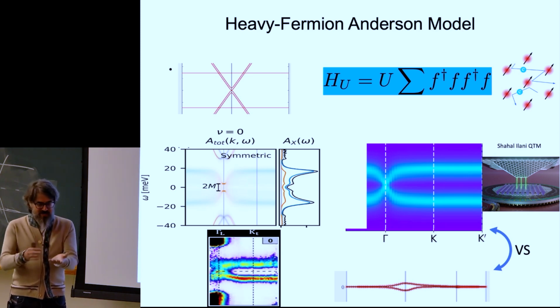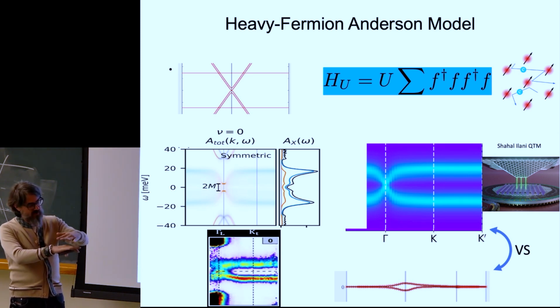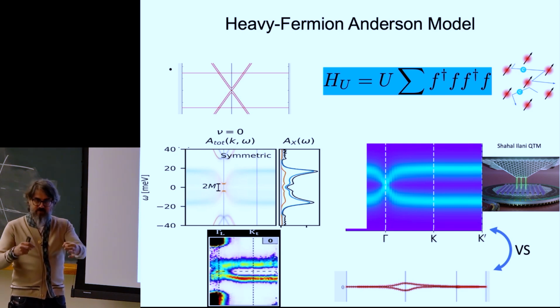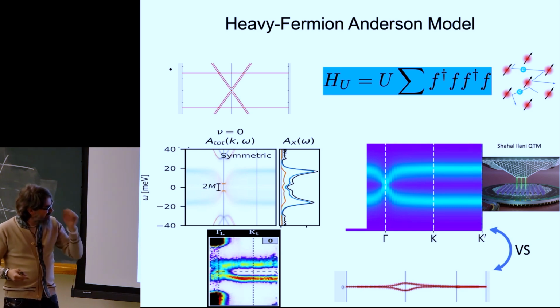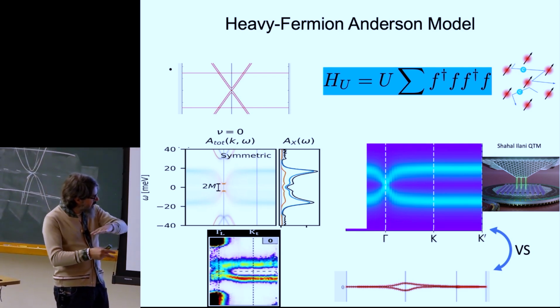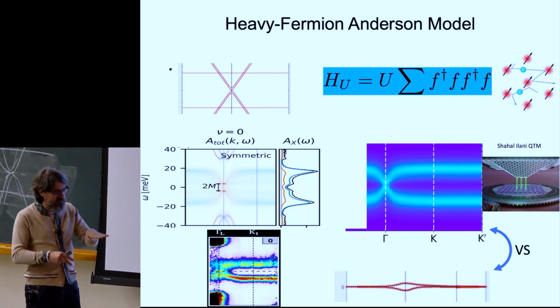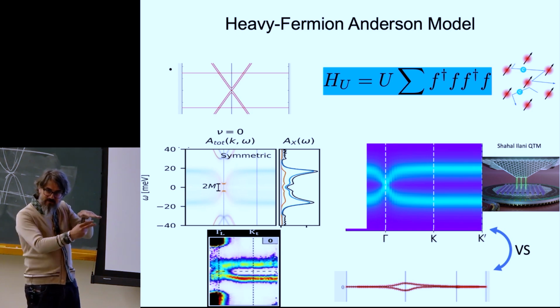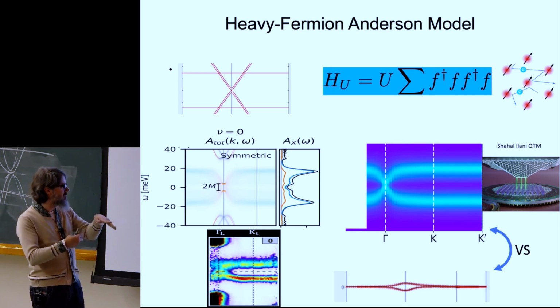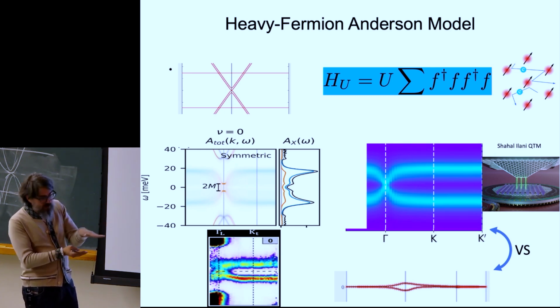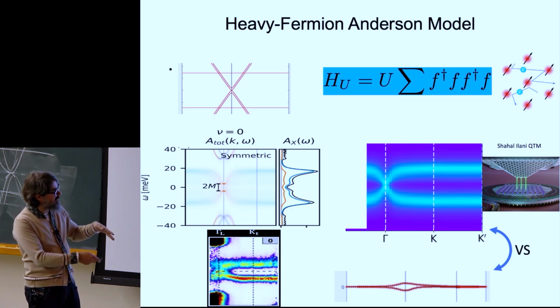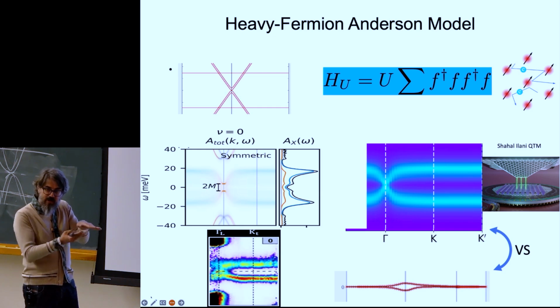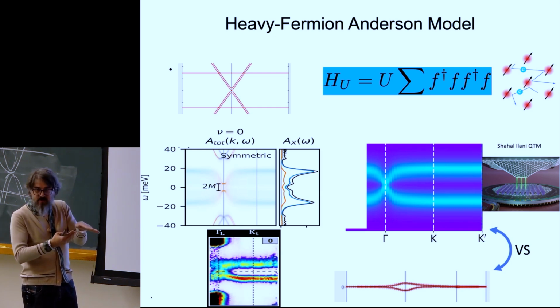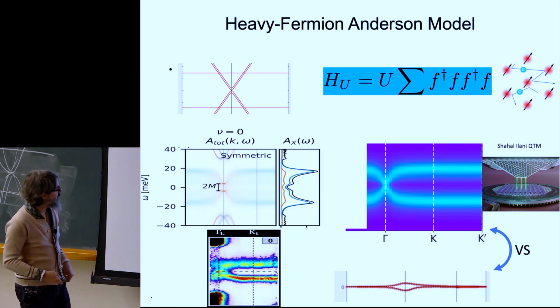So what you do, for people that are not condensed matter, people that are condensed matter know it, instead of having an STM tip, which is not atomistically flat for large distances, this is like a tip that's flat for microns, okay? And I think it's a few, or maybe 500 nanometers, something like this, okay? So you tunnel coherently, and the tip and the sample is the TBG sample, okay? But the tip is coherent tunneling over 500 nanometers. And then you get momentum resolution also by just Fourier transforming.